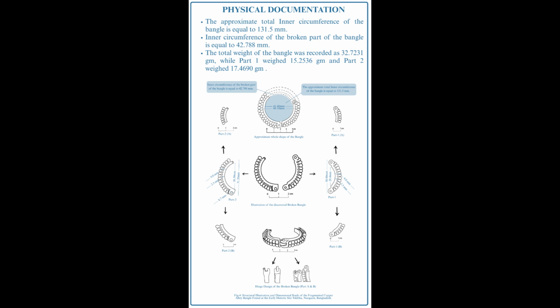Before conducting the scientific analysis, we first carried out a thorough physical assessment of the artifact. The bangle was found in two fragments. Unfortunately, we didn't find the broken parts of the bangle. Its total inner circumference was approximately 131.5 millimeters, with one broken segment measuring just over 42 millimeters. The two parts weighed 15.25 grams and 17.46 grams, respectively. These basic measurements were essential for evaluating its design, wearability, and for guiding our sampling process.